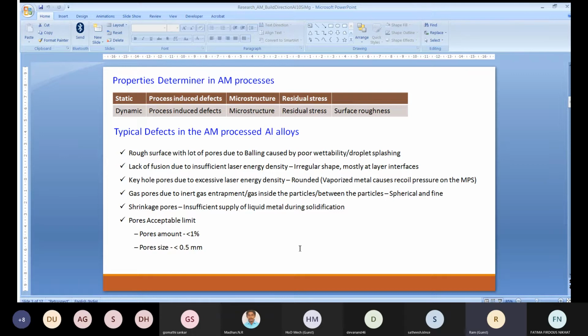What are the property determiners? If you see, one is the defect in the component, second is the microstructure you get in the component, third is residual stresses. These three dictate static properties. In the dynamic case, in addition to these three, surface roughness also plays a vital role, because fatigue crack initiates on the surface.